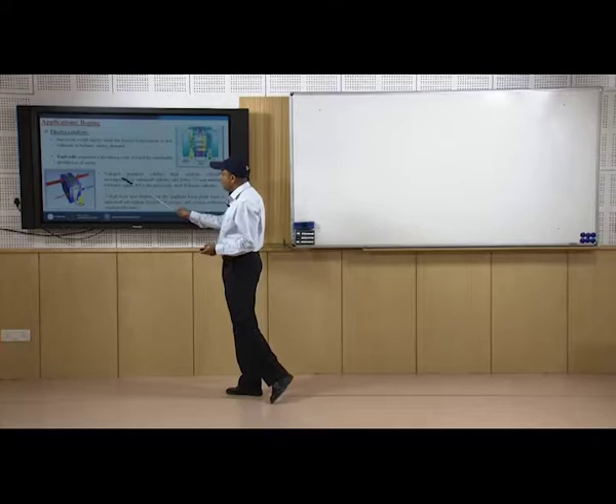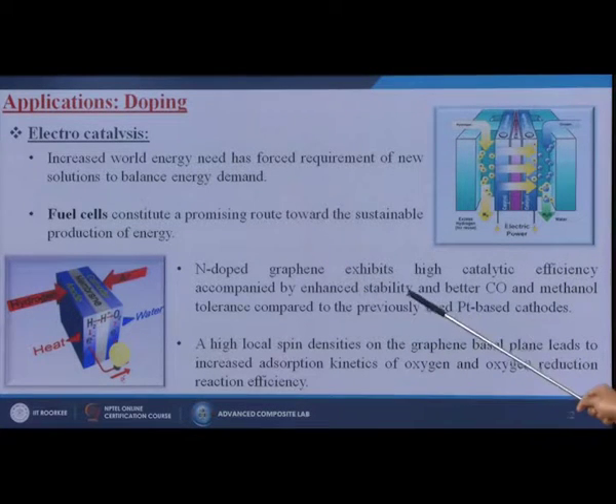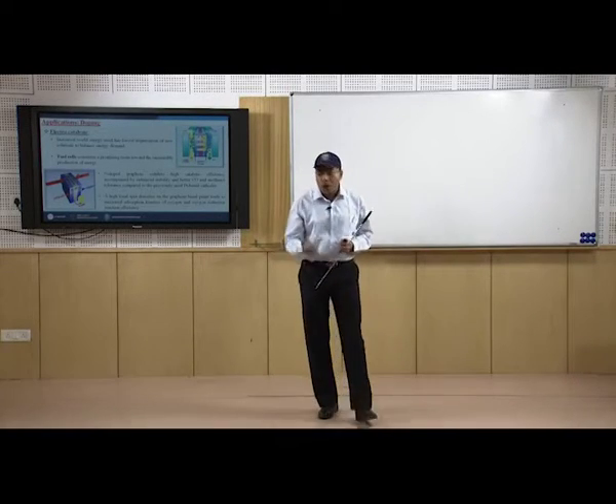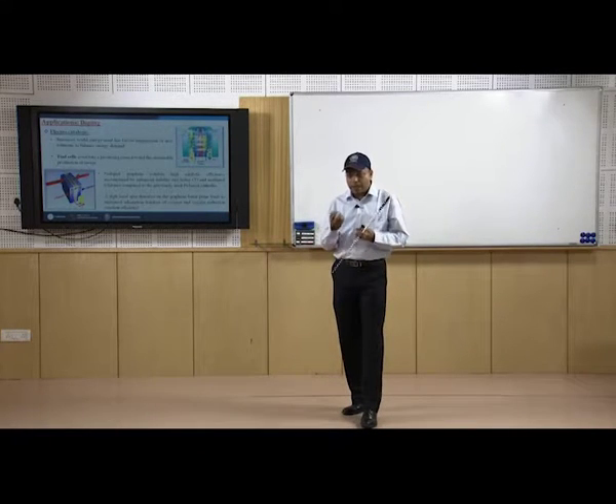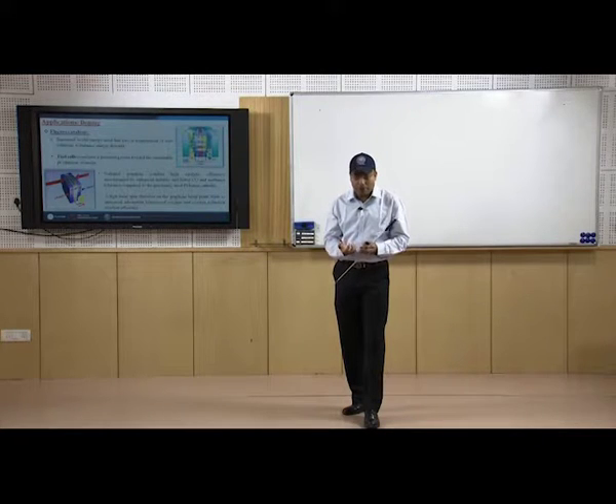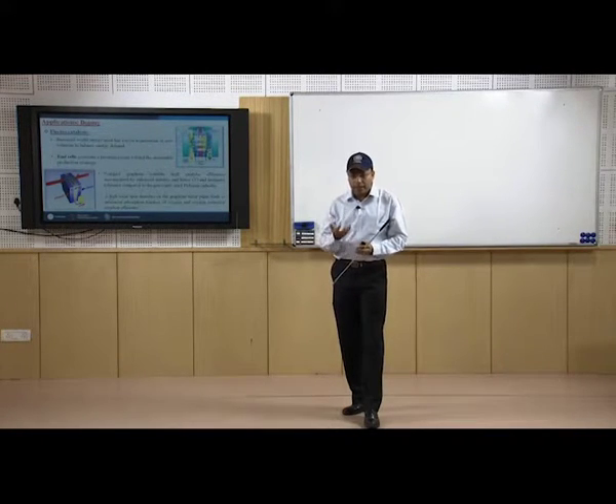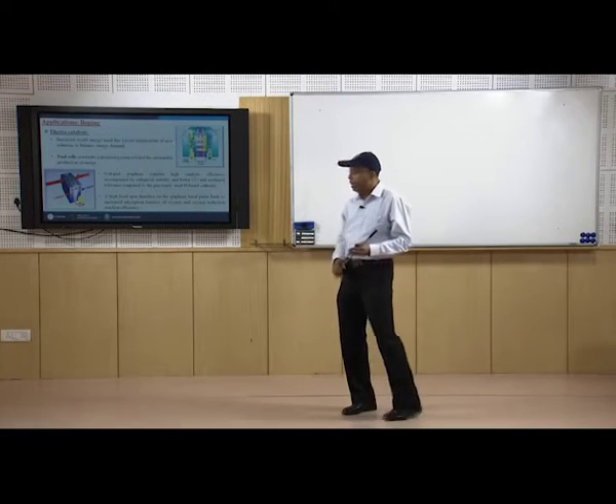What we are going to show is that N doped graphene exhibits high catalytic efficiency accompanied by enhanced stability and better carbon monoxide and methanol tolerance compared to the previously used platinum based cathodes. Previously we used materials which generated carbon monoxide or methanol inside the system, and such a material can't sustain, or toxic gases can come from those techniques, creating hazards to the environment. So nowadays we are trying to use nitrogen doped graphene, which can be readily made in our laboratory and can tolerate carbon monoxide or other toxic gases generated inside the system, so that this material can be used for a longer time.